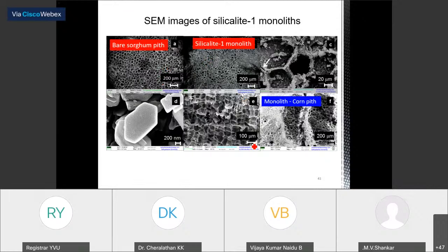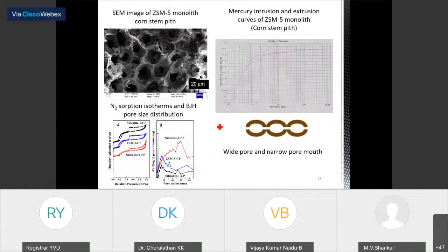So if you look at the scale, you can see we have all these macropores. Based on the scale bar, you can understand that. This is a macropore. So if you look at the further characterization, you can see in the nitrogen sorption, we have mesopores as well as micropores. So micropores are coming out from the zeolite structure, and these mesopores are coming out from the pores which are produced by synthesizing this material in the presence of this natural material.